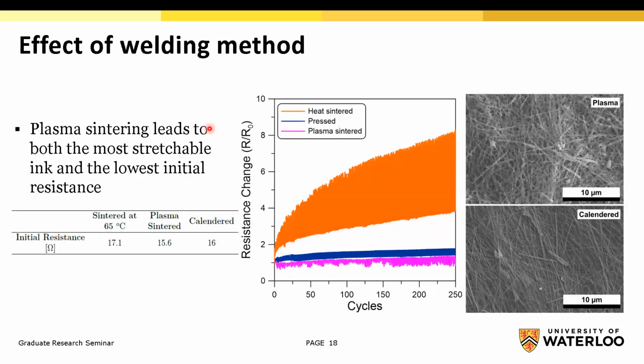Another study that we did was the effect of welding method. In order to do that, we compared thermal sintered, plasma sintered, and calendered silver nanowire inks. We compared the thermal ones with silver nanowire inks that we plasma sintered with oxygen plasma, and we calendered with a hot rolling machine, but at room temperature. You can see plasma sintering is making the nanowires nanoporous, and calendering is making a more planar surface of nanowires. All of the nanowires stick to the surface after rolling twice, and they have a much more planar network.